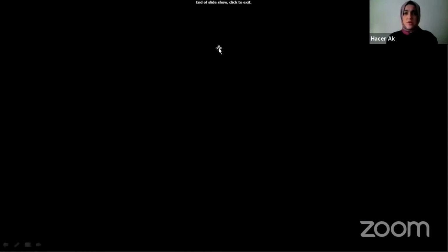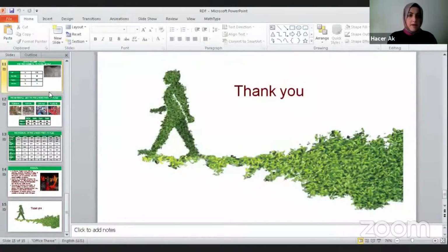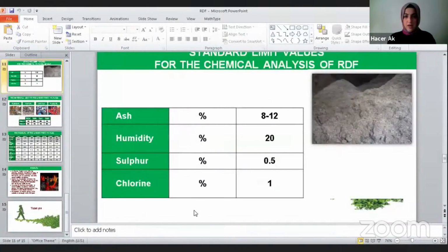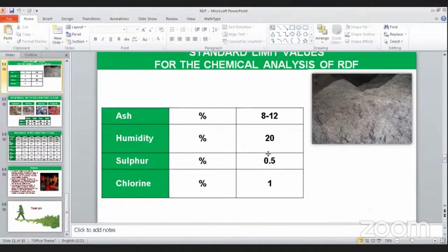I have shown them here. Humidity should be below 20%. Sulfur content should be 0.5%. Chlorine content should be less than 1%. And ash content should be between 8 and 12%. So this is the standard for your RDF product? Yes. Okay.